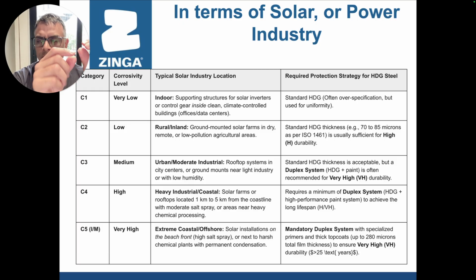But the issue is that the so-called zinc-rich coatings in the market are really not zinc-rich. They contain 60 to 65% zinc. Now, we are the only coating in the world having 96% zinc in dry film thickness, and we say that with a lot of responsibility and a lot of tests. The American Galvanizers Association defines galvanizing as a process imparting 95% zinc or more in dry film thickness. So we are known as film galvanizing.